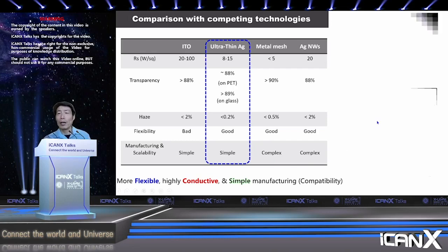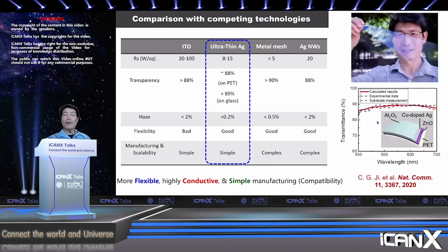So another work. If you coat the metal film onto a plastic, right, typically it's going to be a little bit more opaque. But we found through this work that by proper design, after coating these multiple layers, you can make the film even slightly more transparent than the plastic, the PET itself. That's me holding a piece of glass. You can see it's very transparent. And this is actually not violating any fundamental physics. The trick here is that these multiple layers together function as a type of anti-reflection. So it actually increased the light transmission slightly.